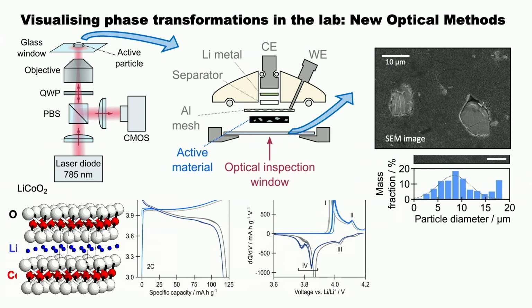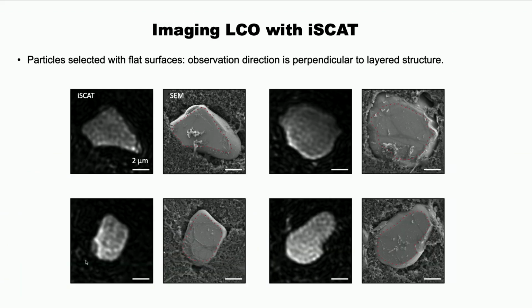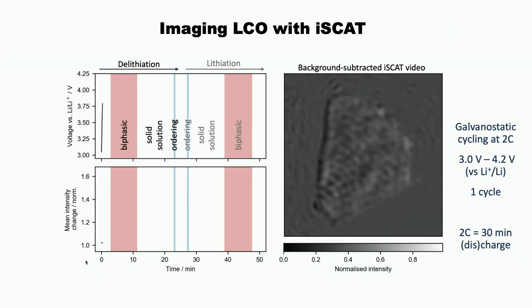So lithium cobalt oxide has a metal insulator transition, which is this peak here that is shown in the dQ/dV plot, and this process is an ordering transition at Li 0.5 that I'll explain in a few seconds. So this was the first imaging of iSCAT. So what you're seeing is the SEM, and these are the pictures. And we're focusing on the flat parts of these particles, but we're going down about 300 nanometers. So this is not a surface method. We are really looking at bulk phenomena.